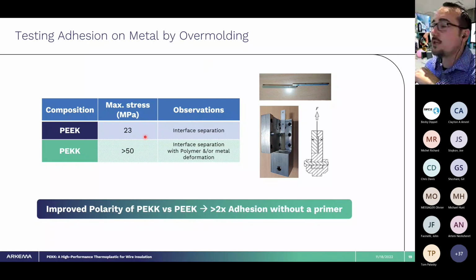In the PEEK material, we're seeing interface separation, which means the polymer is peeling off of the bare metal substrate. In the case of PEKK, we are seeing interface separation, but we're also seeing polymer deformation and some metal deformation, which means we've really got a nice bond to that metal, so very good bonds to the substrate.